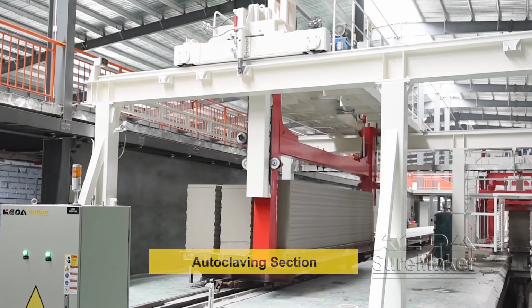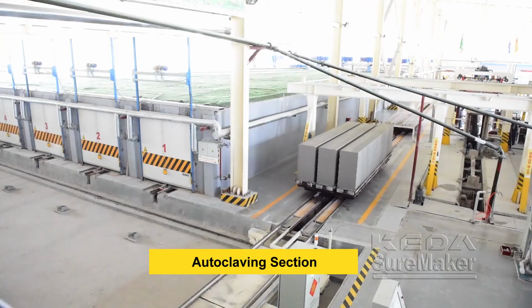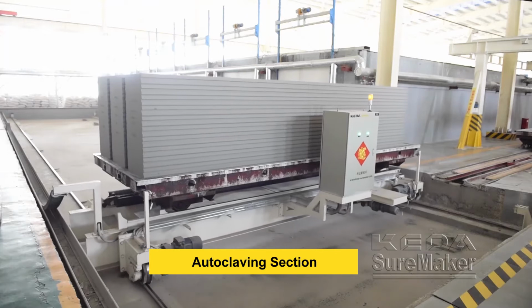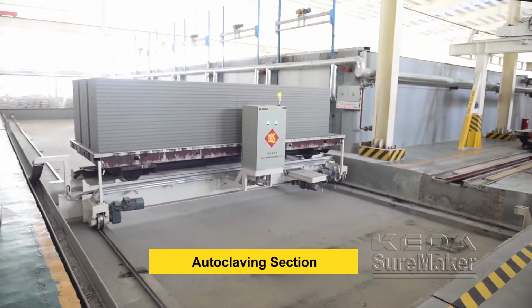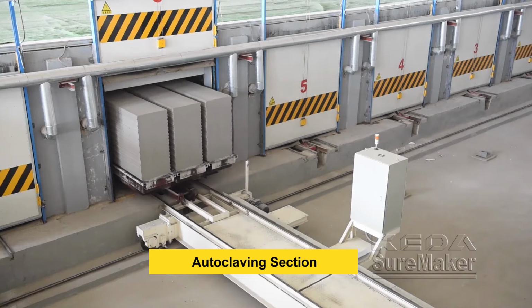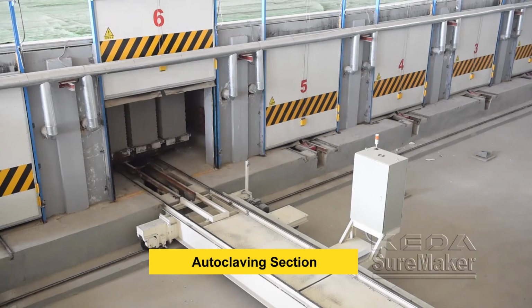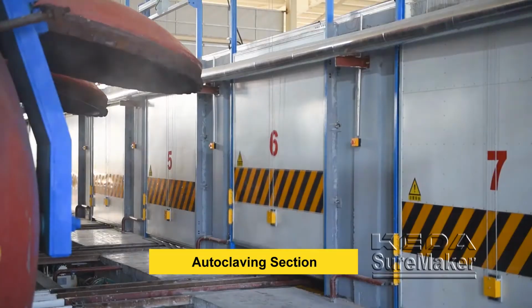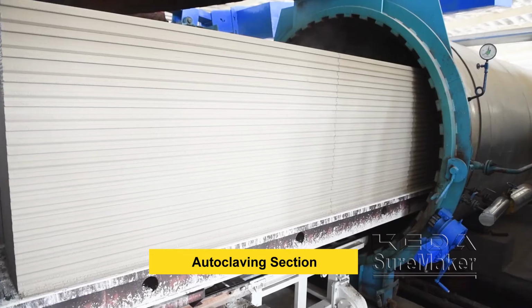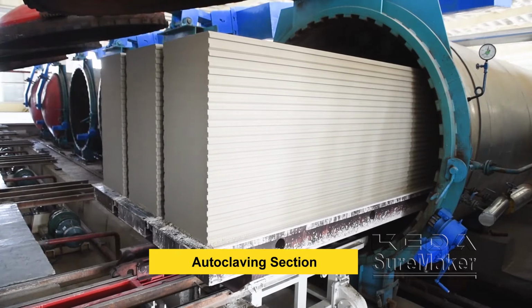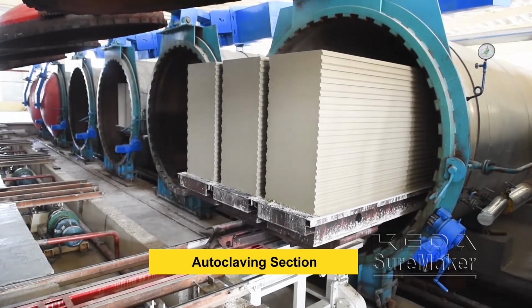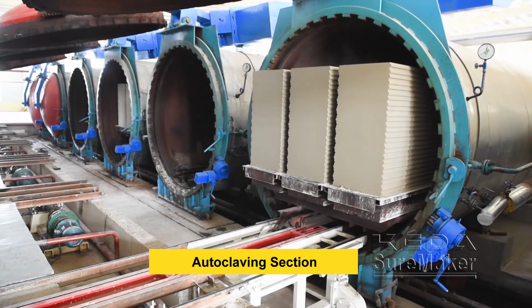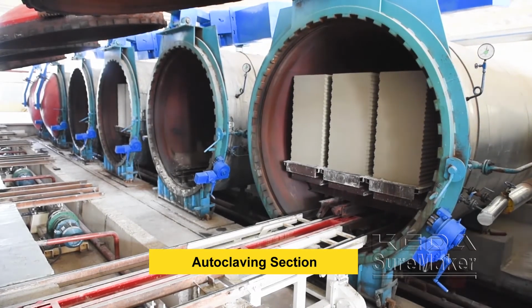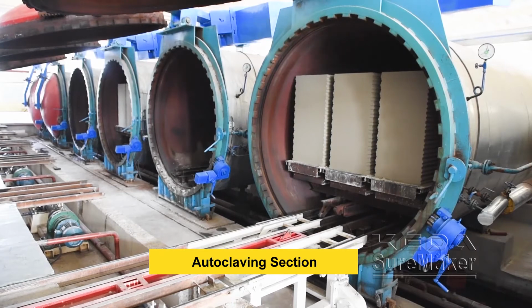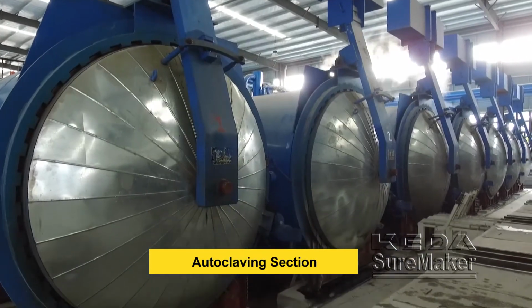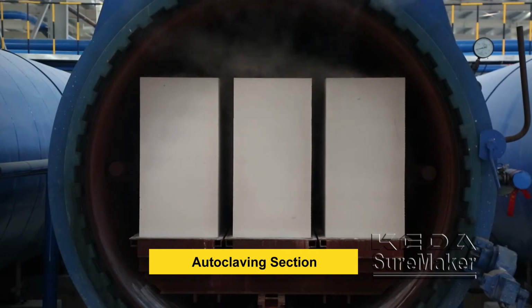The semi-finished product stacking machine transfers the green cakes together with side plates onto the 3-mold curing car. Then, the ferry car will take them for grouping before autoclaving. After grouping, 3 mold curing cars will be pushed into the autoclave for curing 10 to 12 hours under 200 degrees Celsius, 1.2 megapascal. Steam and autoclave can be reused from each other to save energy consumption.